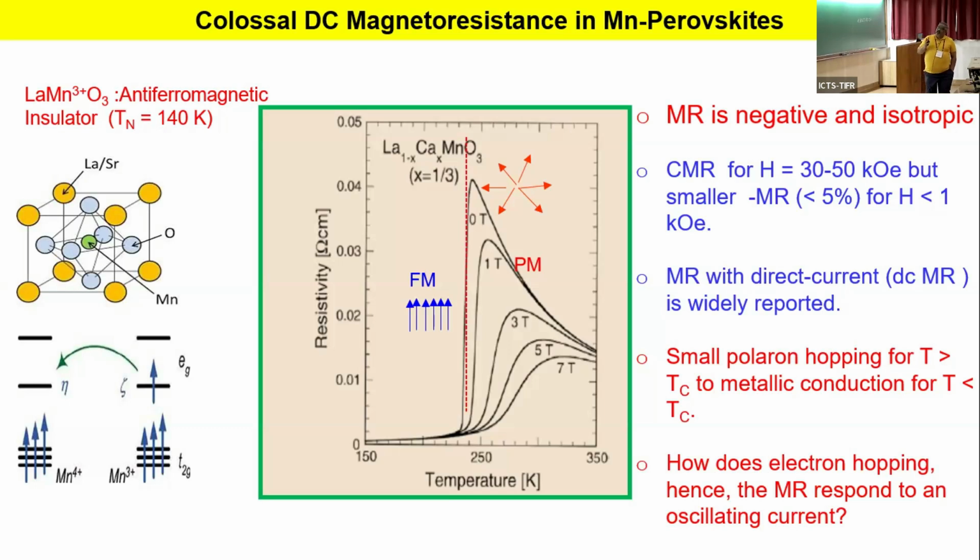So this talk mainly focuses on magnetoresistive oxides, particularly the manganese perovskites. Starting with that, the compound lanthanum manganese oxide is an antiferromagnetic insulator, and it has only manganese 3+. But if you replace lanthanum with strontium, which is divalent, basically you introduce holes. That means you partially change Mn3+ into Mn4+, which has 1 electron less in the eg band. So the eg electron will hop from Mn3+ to Mn4+, and so on. But hopping is easier if the spins on the t2g levels are aligned parallel.